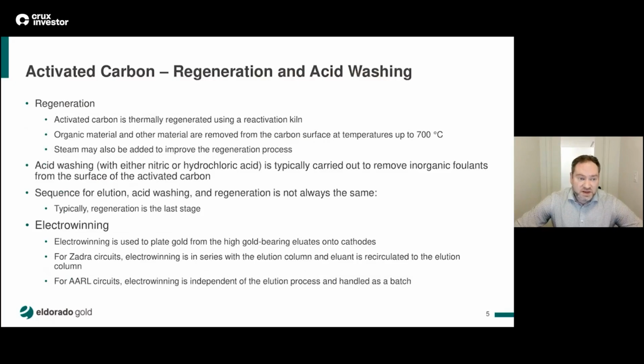Once the carbon has been eluted, it can be regenerated, and this is done typically using a reactivation kiln, where the material is heated up to temperatures of 700 degrees Celsius, and in some cases steam is also added to aid in the regeneration process. Acid washing, either using nitric acid or hydrochloric acid, is used to remove inorganic foulants from the surface of the carbon. The actual sequence for elution, acid washing, and regeneration is not the same.